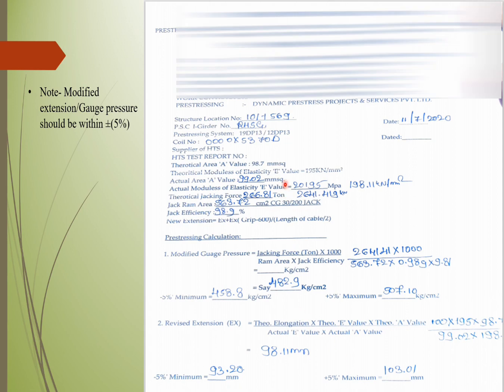We need to calculate the modified gauge pressure. The manufacturer has provided the jack efficiency as 98.9%. The modified gauge pressure equals jacking force divided by ram area, divided by jack efficiency, multiplied by 1000. This gives a modified gauge pressure of 482.9 kg/cm². Since the permissible tolerance of modified gauge pressure is ±5%, the minus five percent comes to 458.8 kg/cm² and plus five percent comes to 507.10 kg/cm².